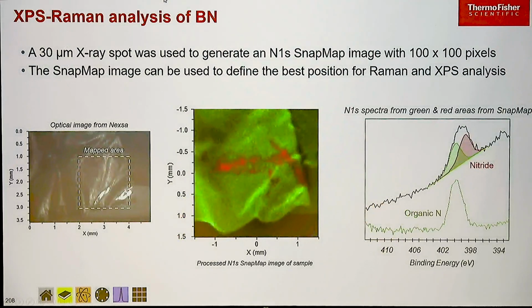Unfortunately, they weren't very good at preparing the boron nitride film, but it did make a really great sample for showing the way that you can do this workflow of XPS and Raman. So this is the sample over here on this side. This copper film should have had a continuous layer of boron nitride over it, but actually this red area here in this nitrogen image is the only part where there's actually any boron nitride. The green is all this organic nitrogen component, which is just the precursor that hasn't reacted. So it's only been very partially successful in terms of synthesizing it.